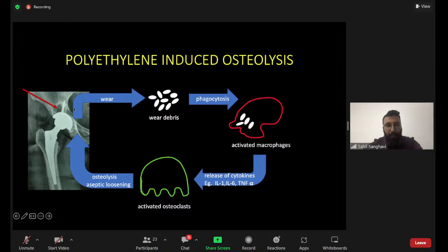So what was basically happening was that the wear of the polyethylene would cause wear debris, and this wear debris would then undergo phagocytosis by activated macrophages. These activated macrophages, in turn, would release cytokines like interleukin-1, interleukin-6, and tumor necrosis factor alpha, which would activate osteoclasts. Once these osteoclasts were activated, it would lead to bone resorption, that is, osteolysis and subsequent aseptic loosening of the implant. So that was the pathophysiology of polyethylene-induced osteolysis.